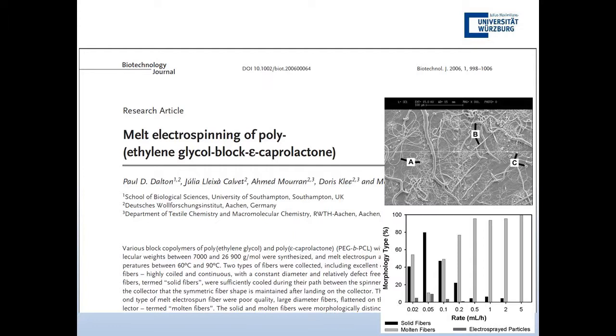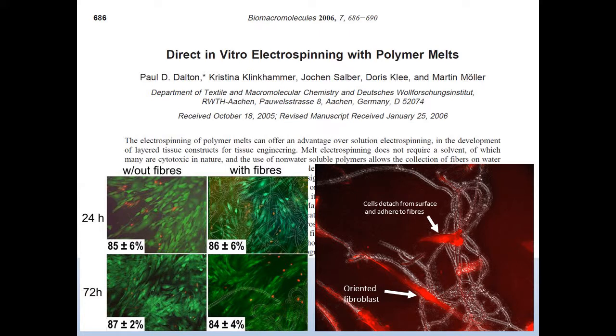So back to this kind of mess that we got. We tried to characterize it a little bit and work out, even though we're getting a spectrum of different materials, we tried to characterize a little bit between the solid fibers, the ones in black that we wanted, and we could see that one of the parameters that was important was the flow rate. That, you know, if you were to use a milliliter per hour to spin onto cells, it was a really awful, messy experiment. The quality of the fibers was bad.